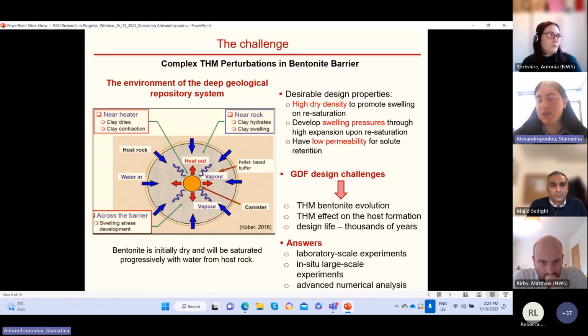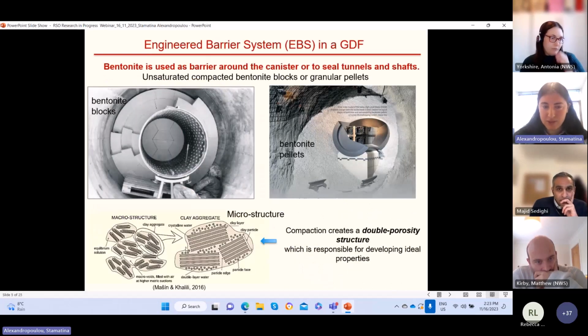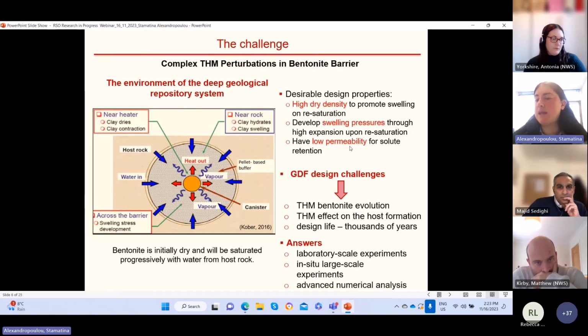Another important property of bentonite material is that it needs to have low permeability for solute retardation. And just to explain, that is actually because of the double porosity structure that we saw right here. Upon contact with the water, the clay aggregates will expand and will fill these voids that we can see here. So the microstructure will dominate over the macrostructure. And therefore, that means that the permeability will be reduced. And if at any point in time, because of the long-term corrosion of the nuclear waste canister, radionuclides escape, this process will be really slow. So this is a very important property of the bentonite material.